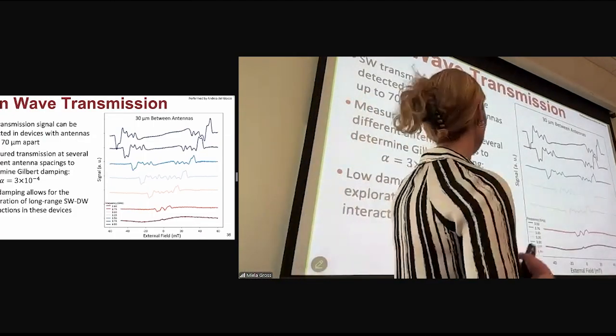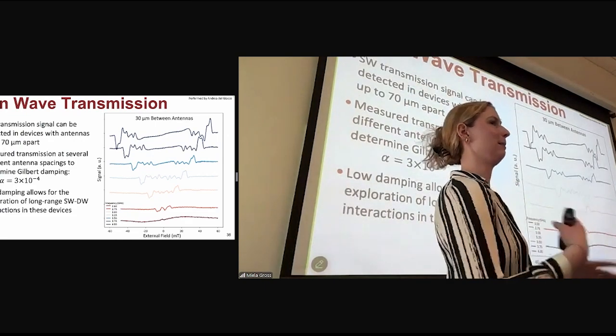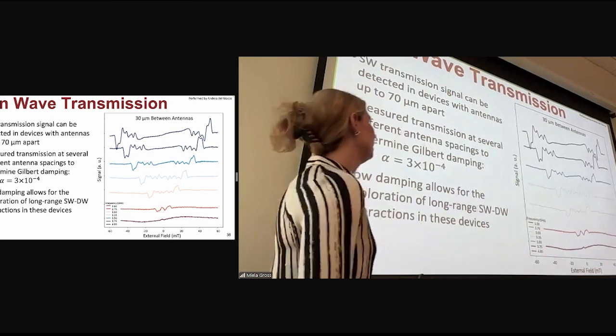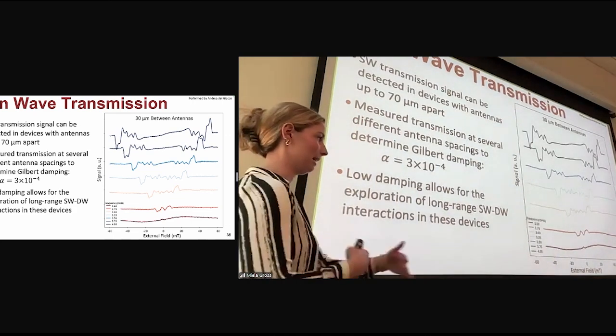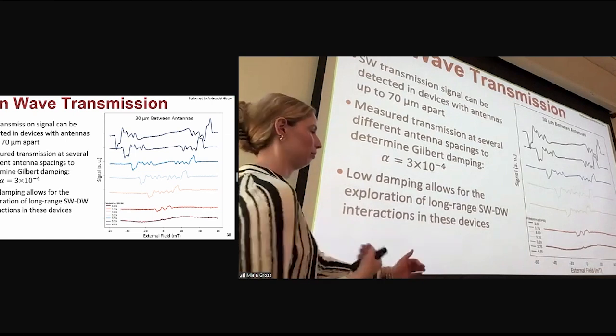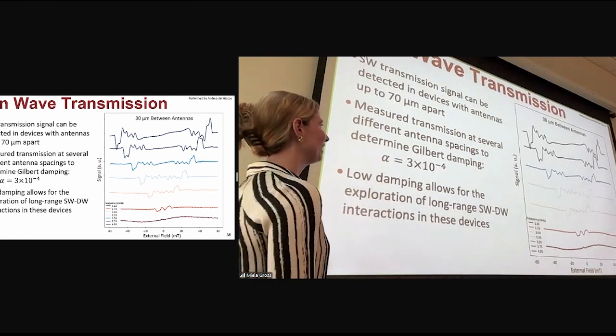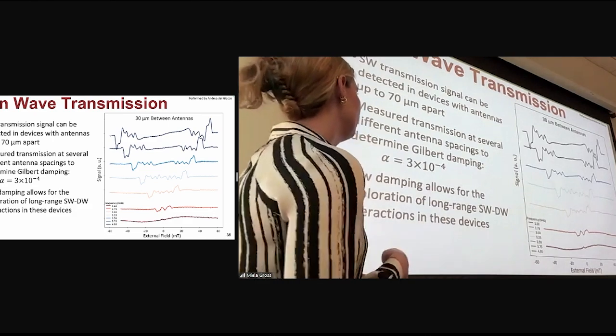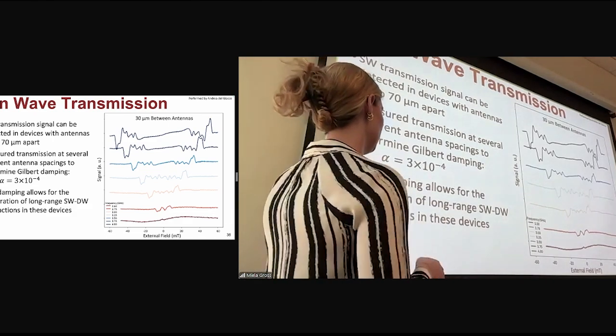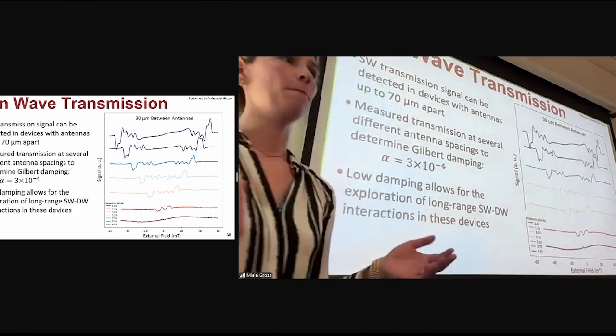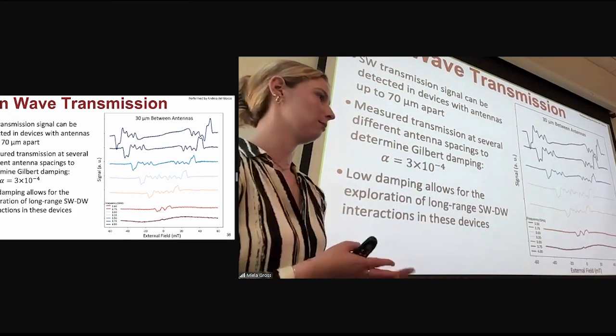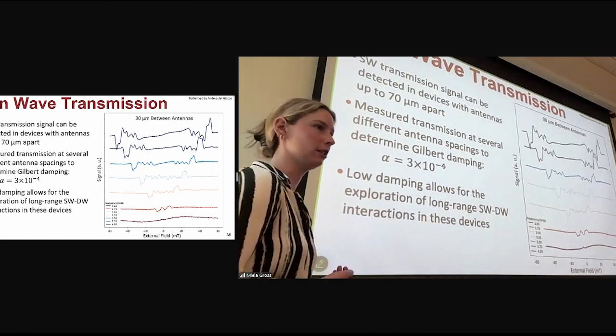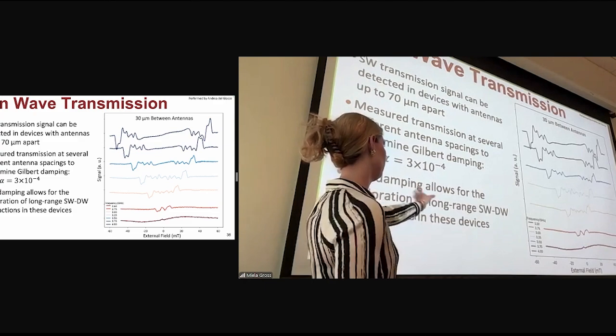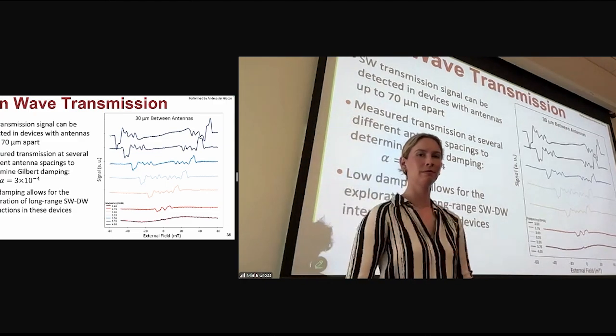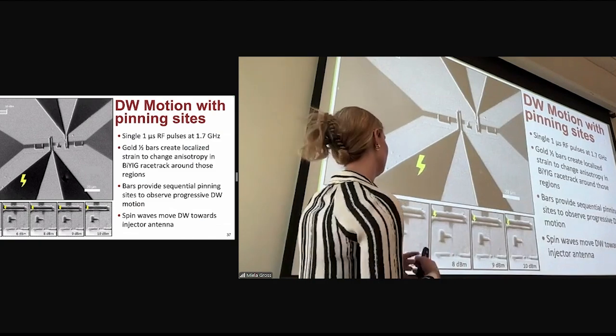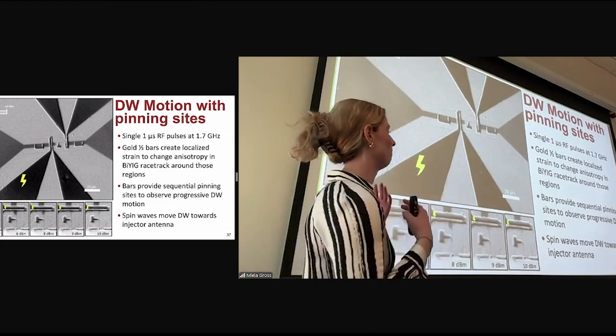So now we're looking at spin wave transmission, again, more characterizing the magnons and the spin waves in our bismuth-YIG devices. We were able to show spin wave transmission between two antennas up to 70 microns apart. So that's pretty far apart for a magnetic material. And we're able to use that information to back out the Gilbert damping constant of our bismuth-YIG, which was 3 × 10⁻⁴. And that's a very low value, and low damping corresponds to fast domain wall motion and very long decay lengths of our spin waves, which allows us to explore long range spin wave domain wall interactions in these devices.